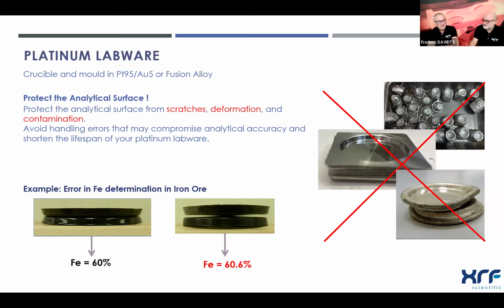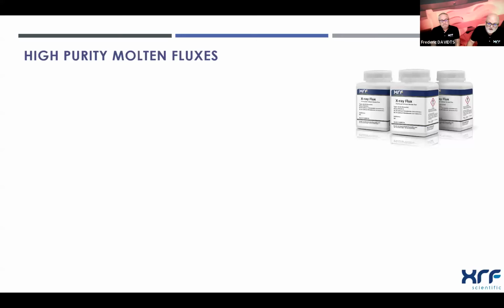It's very important. And the reason here is that if we have a curved sample, the sample is close to the X-ray tube, and of course we get a higher concentration because we have more excitation of the elements. Exactly. The distance is not the same with the detector. Okay. So the fluxes we already spoke about.